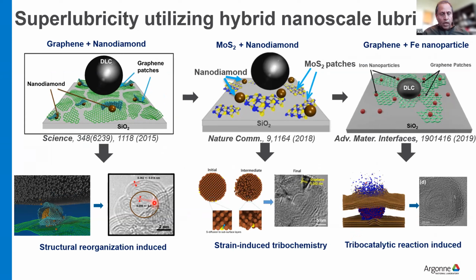In the case of graphene and nanodiamond, we have structural reorganization, but in the case of MoS2 and nanodiamond, there is very interesting tribochemistry at play. At high contact pressure, there is a disintegration of MoS2, and the sulfur diffuses into the nanodiamond, produces a lot of strain, and destroys the nanodiamond completely. It then forms this beautiful onion-like carbon structure, which again acts as a nanodiamond and gives rise to superlubricity. Now, in the case of graphene and iron nanoparticles, there is an exothermic reaction between the iron nanoparticle and graphene, and the graphene layers get destroyed. Again it forms this beautiful onion-like carbon structure, which finally gives the superlubricity.